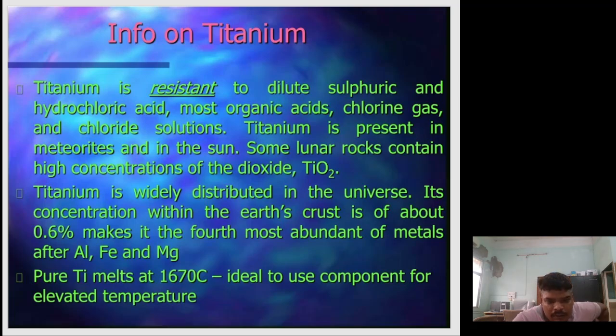The world production of titanium is nevertheless very small. 80% of all the titanium produced is used in the aerospace industry. Car suspension springs could easily be made of titanium with a great reduction in weight, but titanium is not available in the large quantity needed and certainly not at the price required for automobile application. The price of a mill product is in excess of 25 pounds per kg compared to 5 pounds per kg for steel. This is principally due to titanium's strong affinity towards oxygen, both during extraction and downstream processing. The target price for titanium needs to be reduced to about 30% of its current value for serious application in